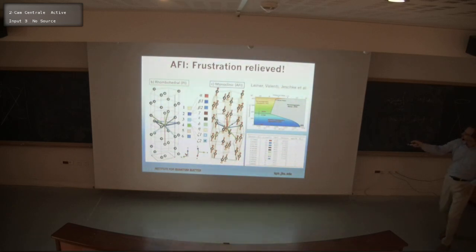every single pair of spins which is, let's say, ferromagnetically correlated like these two, they have a ferromagnetic exchange interaction. And every single pair of spins which is antiferromagnetically correlated in the ordered state, they have an antiferromagnetic interaction. So it's basically a completely happy and certainly not a frustrated magnet at all. It's just gone into a wonderful arrangement of all the exchange interactions that allows it to go deeply into an